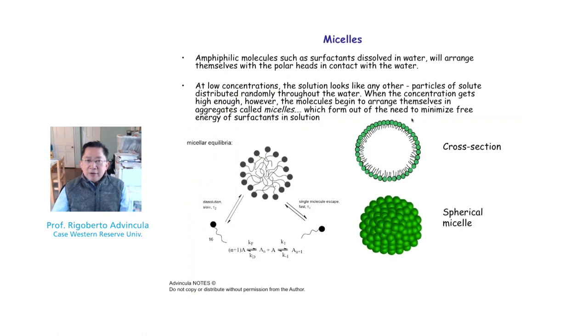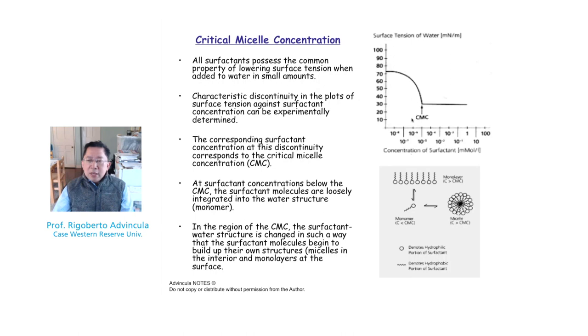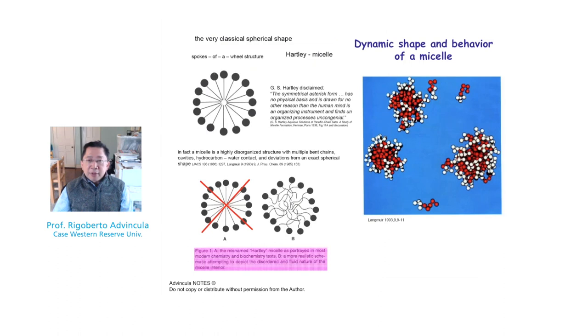A very common term associated with surfactant assembly is micelles. Micelles are often thought to be spherical, but they are quite dynamic — they form, reform, and exchange between micellar structure and the matrix fluid. We measure them by looking at surface tension, dynamic light scattering, or conductivity, giving us a value called the critical micelle concentration (CMC). The CMC denotes the minimum concentration at which a micelle is observed. Single surfactants are called unimers.